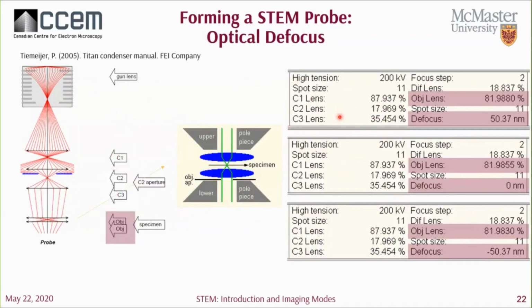In the system, the objective lenses are used for optical focusing, so changing the defocus and focusing the probe on the specimen. Here you'll see that we have zero defocus in this image, and the probe is focused perfectly on our 1D specimen, which is this arrow. But in reality, you probably will have some sample with some kind of topology to it, and thus we can use the objective lenses to fine-tune the optical focus. As we increase the objective lens strength, we're placing the crossover point at a position above our specimen, while decreasing the lens strength will position your crossover point below the specimen.